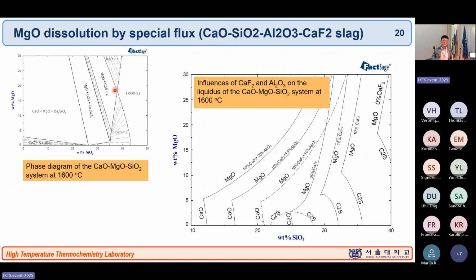And this composition can change widely depending on your slag composition. So for example, this is the starting point, zero alumina, zero CaF2. But if you're adding about 10% CaF2, it moves here. If you're adding 15%, 20%. And with the alumina addition, you can also have a wide range of change of this composition. So if you don't know this composition before, and if you just design your slag without any knowledge like this, then your refractory will be heavily damaged during the operation like this. So the phase diagram is very important.